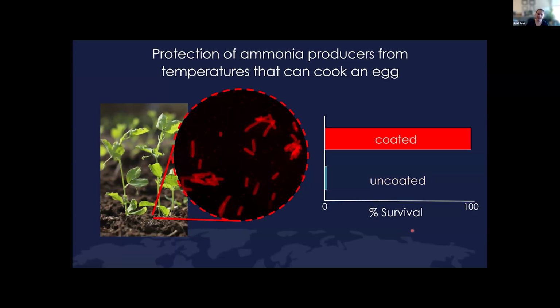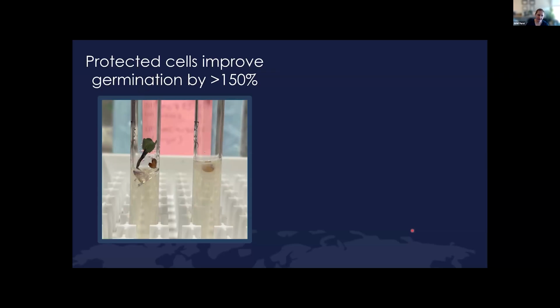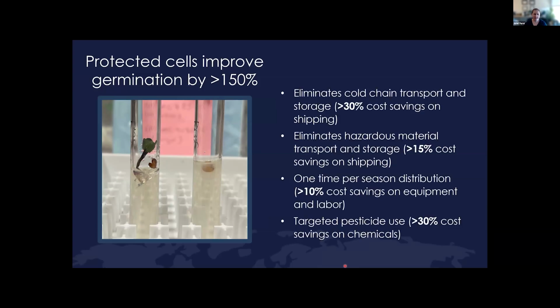What was even more surprising to us than just the difference in microbial survival, though, is that when we apply these to seeds during planting, what we get is a germination rate that's about 150% higher than even the fresh microbes. So our coated microbes that have been dried and stressed are even more effective than fresh, which is really one of the key limitations in regenerative ag right now: the need for growth of your microbes on site.